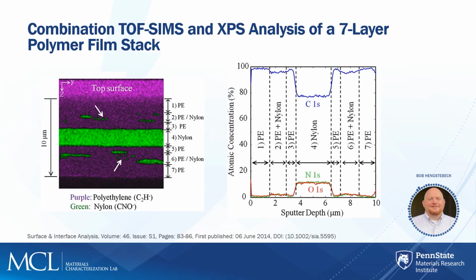And this will be our final example, and in this case, we're looking at a polymer film stack. If we are traditionally trying to analyze this with a traditional ion source, none of this information will be available to us. These materials, which are polyethylene and nylon, would very quickly form graphitic material, would not sputter well, and we would lose all the information in trying to do a depth profile.